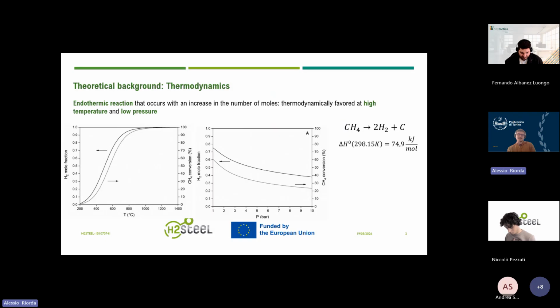And the second point is that during the reaction we also have an increase of the moles of the molecules, because you are going from 1 mole of methane up to 2 moles of hydrogen, so you are increasing the volume. It means that, of course, the pressure is opposing the expansion of the gases. So if you have a higher pressure, your conversion will be lower. And this is clearly represented in the second plot of the slide, where with higher pressure you have a lower conversion. So summarizing, we need a higher temperature and lower pressure to have a good methane cracking reaction.